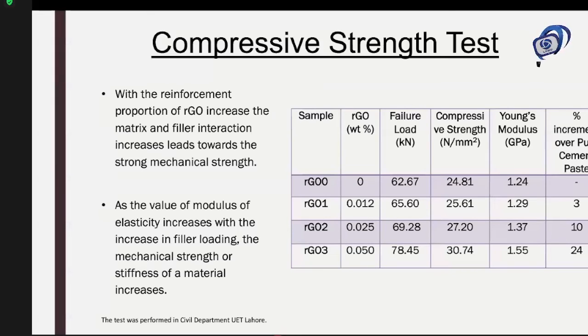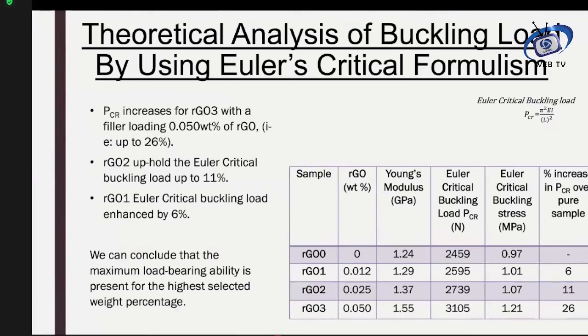The strength corresponding to these failure loads was also calculated by the machine, and it also shows that the inclusion of higher percentages of the RGO has increased the compressive strength. The theoretical analysis of the critical buckling load was also done with the help of the Euler buckling theorem, which shows that it is well in agreement with the experimental analysis.